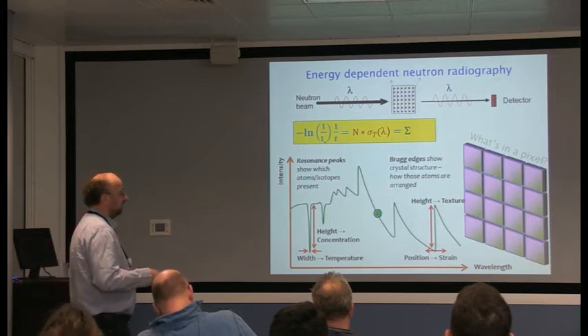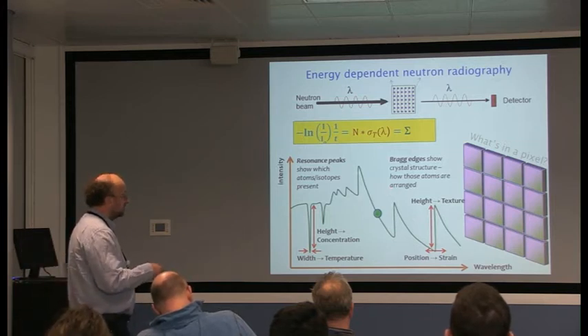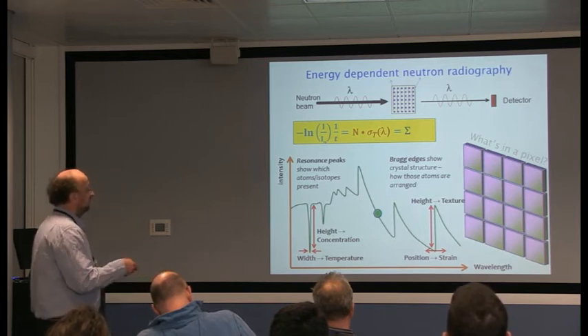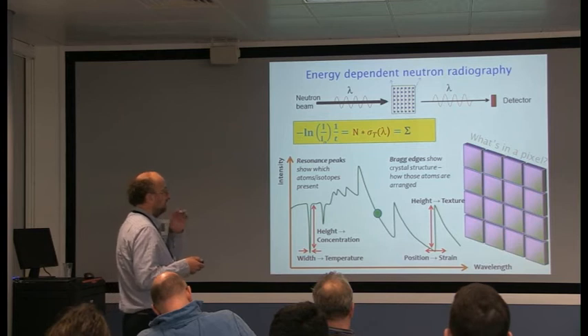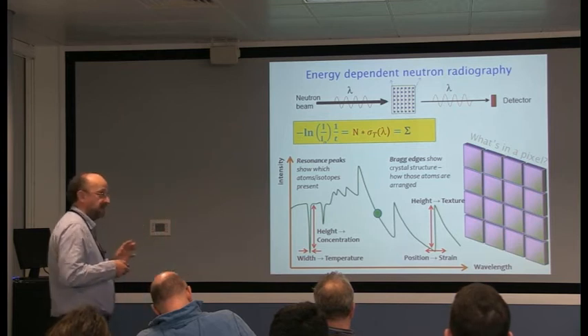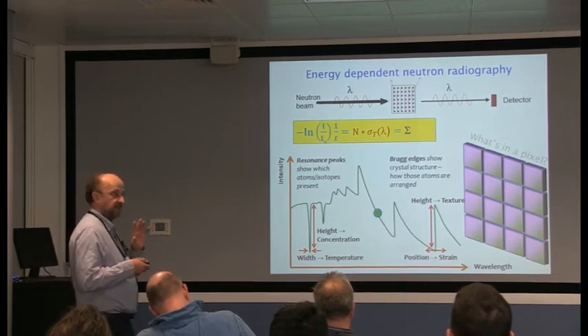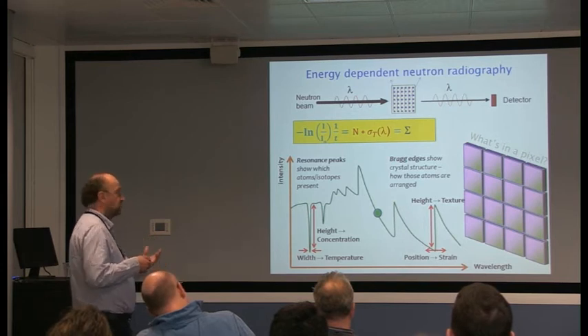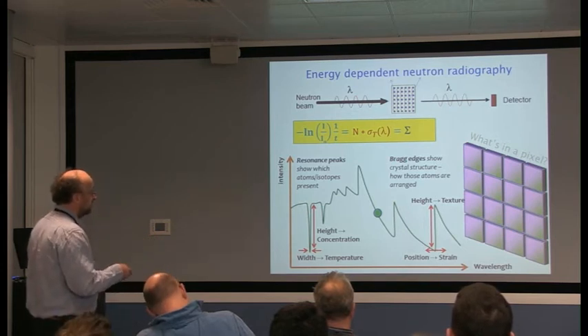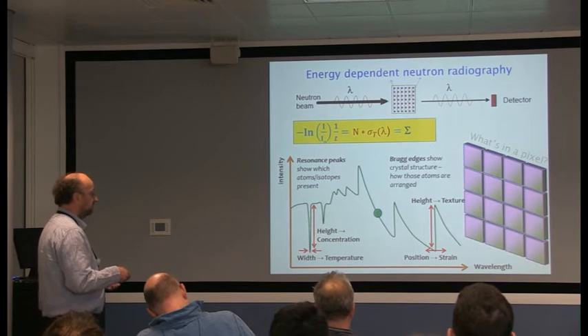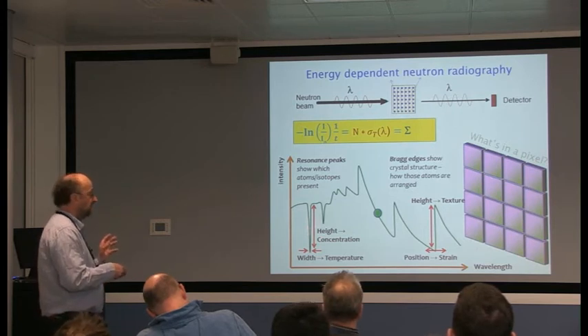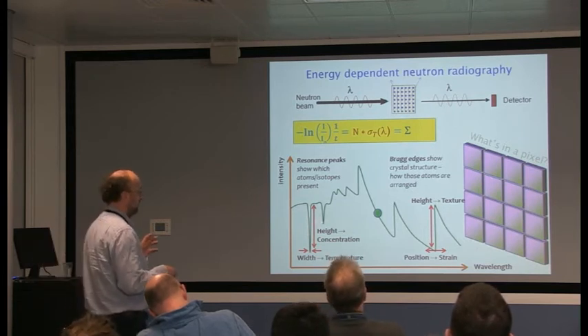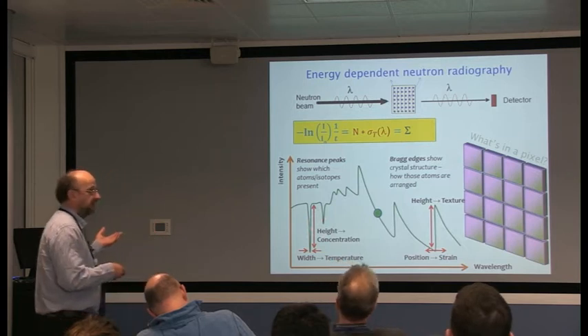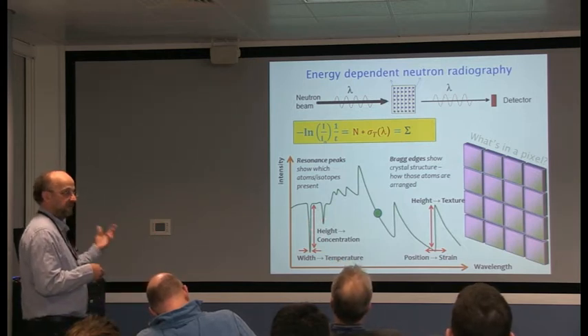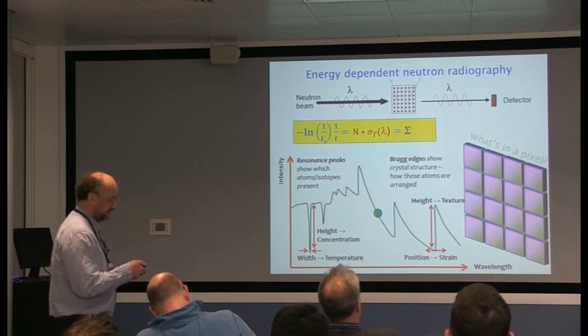So for us it's important to actually analyze those Bragg edges, and this is actually the energy regime of IMAT. There was one comment by Steve about elemental analysis - we are actually starting now a little pilot project to use faster neutrons to determine elements in the bulk, typically of engineering or archaeological materials.